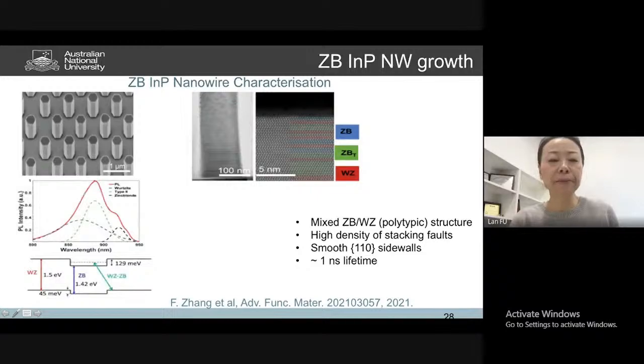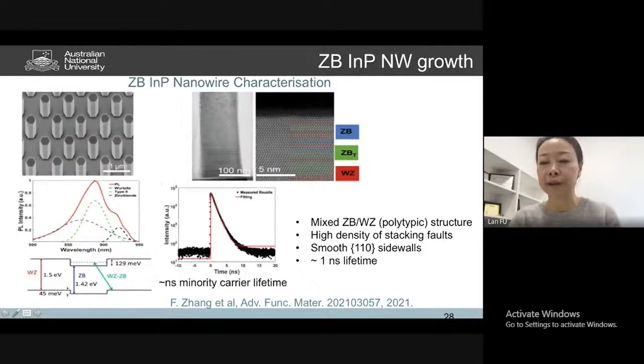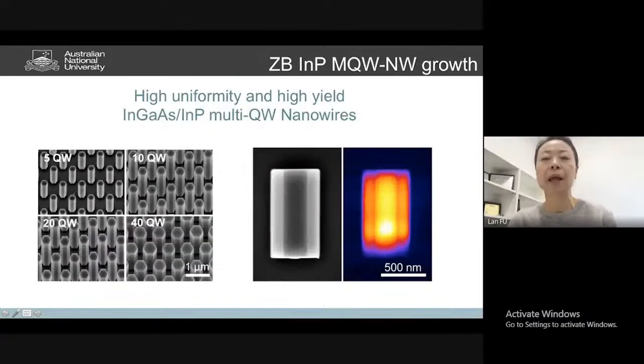And if you look at the photoluminescence, in addition to the wurtzite peak before, we actually have a zinc blende peak. So that's really demonstrating that using this technique, we're able to grow, and the carrier has very good lifetime, indicating good optical property. And by implementing this new growth method of changing the growth window, we can demonstrate not only one quantum well with good performance, we can actually demonstrate 5 quantum wells or even 40 quantum wells with good morphology, as you can see over there.